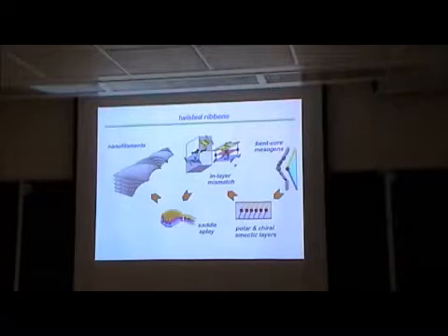As you go out to the edges of the ribbon, it twists, and as you go way out to the edge, the layers gradually become flat. So further out, the layers are flat, but they really want to be saddle splayed, so that costs energy. So rather than make a bigger filament, they'll just grow another one that has the preferred saddle splay.